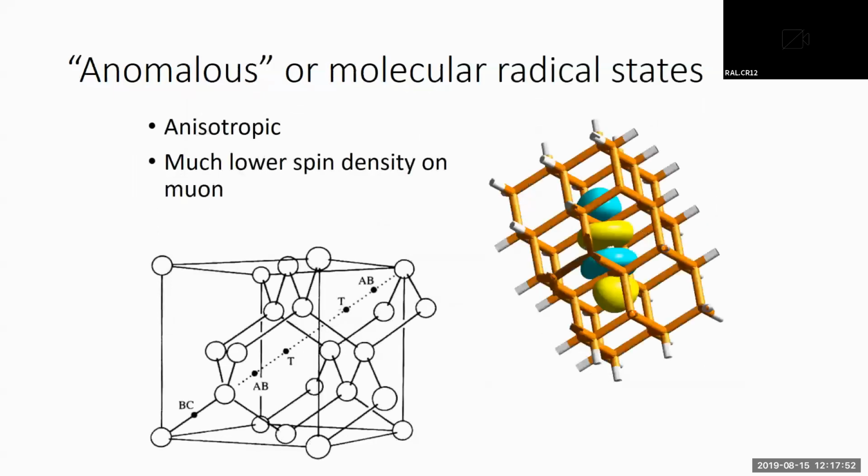Subsequently, we worked out that in practice this corresponds to a muon inserting itself into the bond center. It's like between two silicon atoms. Whereas the normal muonium is in the center of a cage of silicon and is relatively much more like a hydrogen atom.